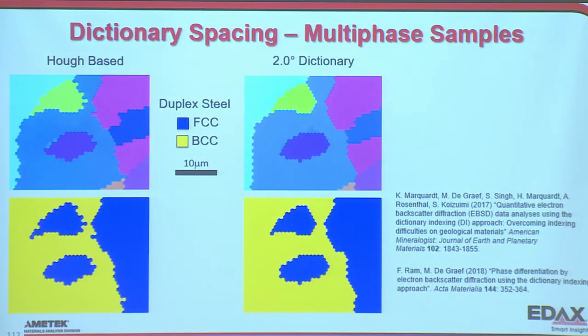And just to show you it works for multi-phase samples, here's Hough-based and here's dictionary. It is interesting, these aren't exactly the same. The Hough seems to bias towards this blue phase in terms of deconvoluting the bands, whereas the dictionary seems to be more even in the way it treats it, which is kind of interesting. So we are seeing some differences at grain boundaries, especially at phase boundaries with this dictionary indexing.